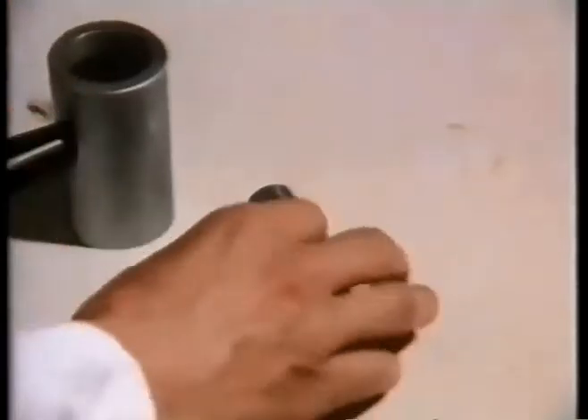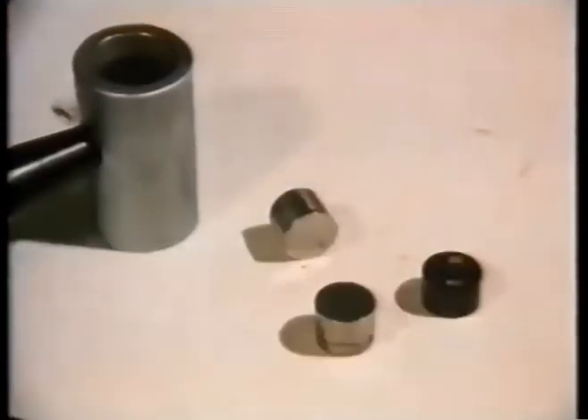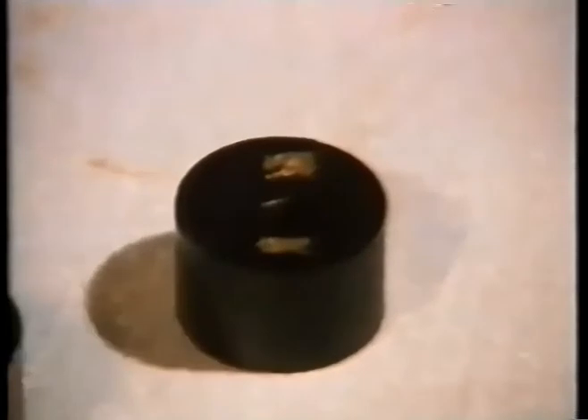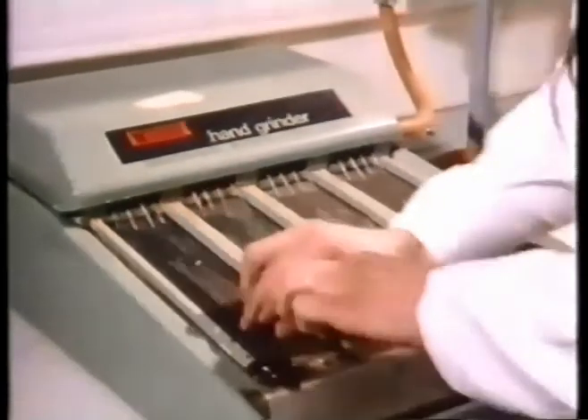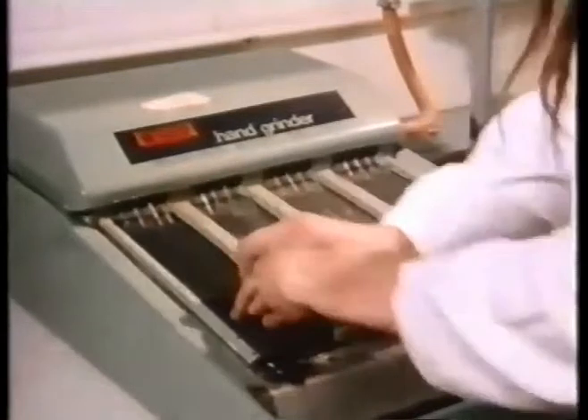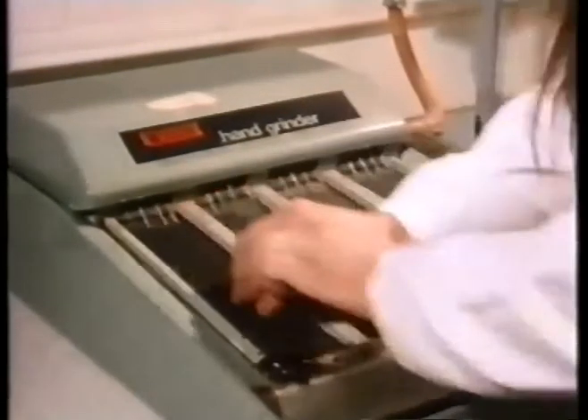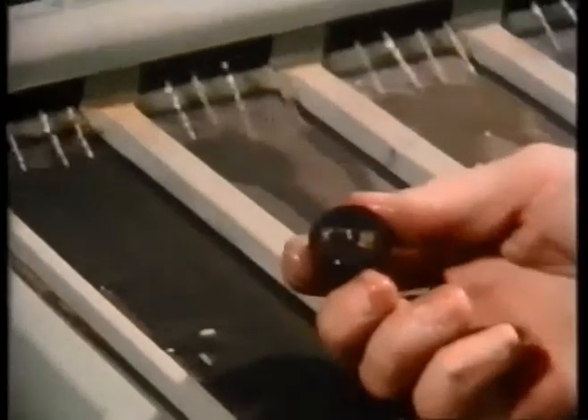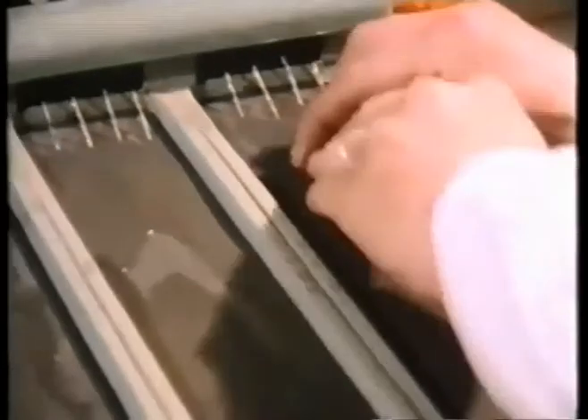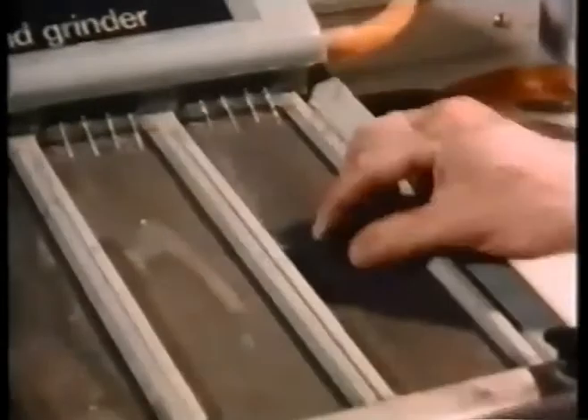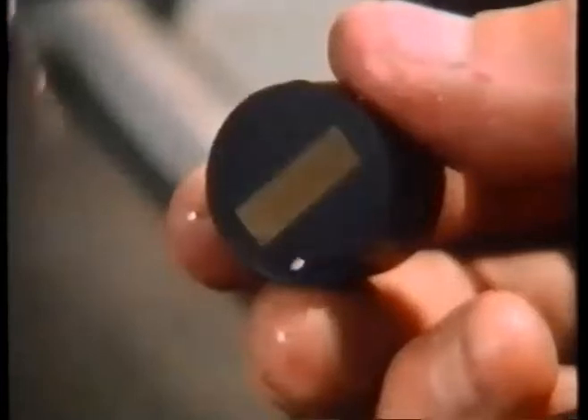The sample is then removed from the mould, and now it's ready for polishing in order to prepare the surface for examination. Polishing starts with silicon carbide paper lubricated with water. This first polish is on relatively coarse silicon carbide with a large grit size. And it's then taken down a series of decreasing grit sizes until the final silicon carbide polish on 600 grade paper, still lubricated with water. The specimen surface improves accordingly.